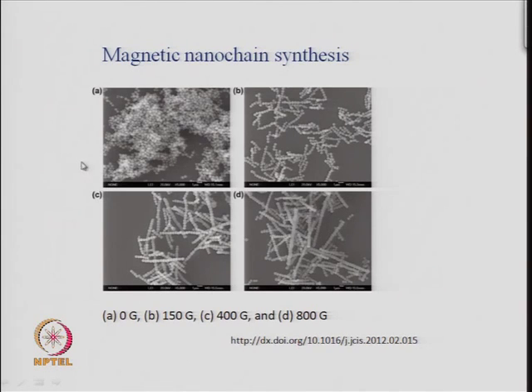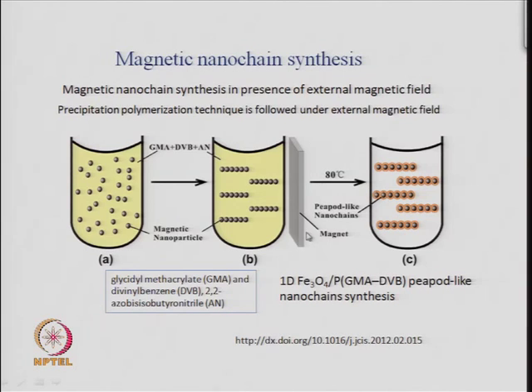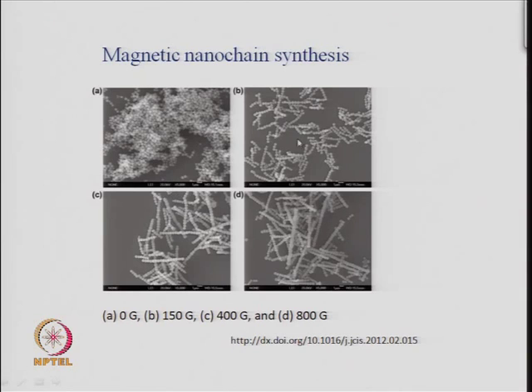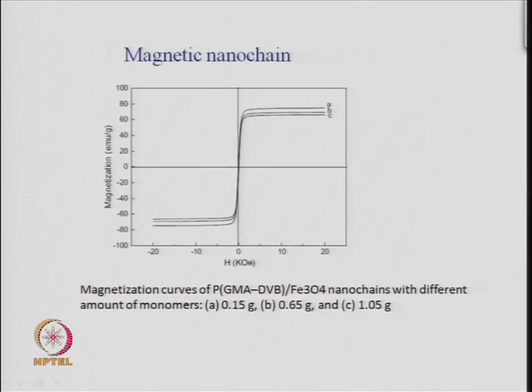So, it tells you that the methodology which we described earlier, bringing a magnetic field to align these particles, is working, and you can get aligned particles like long chains as a function of magnetic field. So, zero magnetic field, no chains, small magnetic field, small chains, and then increase the strength of the magnetic field, you increase the length of the chains of these magnetic nanoparticles. So, this is very interesting for applications.